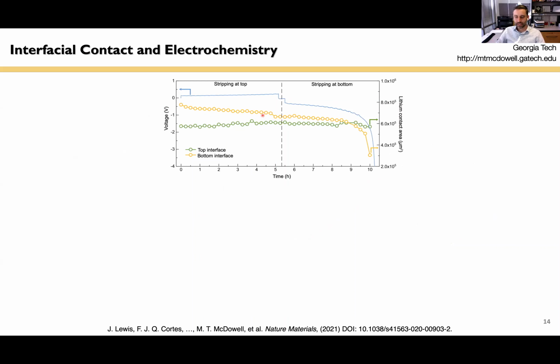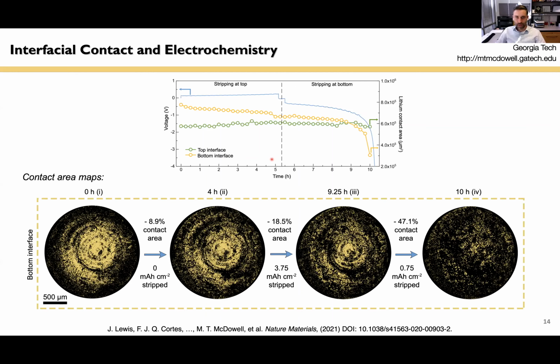And what this data shows is that the top interface doesn't really change very much. The contact basically remains quite similar. At the bottom interface, there's some contact loss when we're stripping on the other side. But then when we start stripping at the bottom interface, towards the end of the experiment, we have a rather dramatic loss in contact and an overall reduction in the contact area. And this happens to correspond with the voltage of the cell polarizing strongly, negative overpotential. And so this is one way of looking at it.